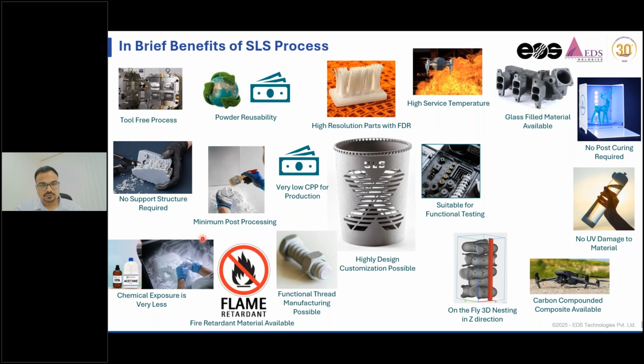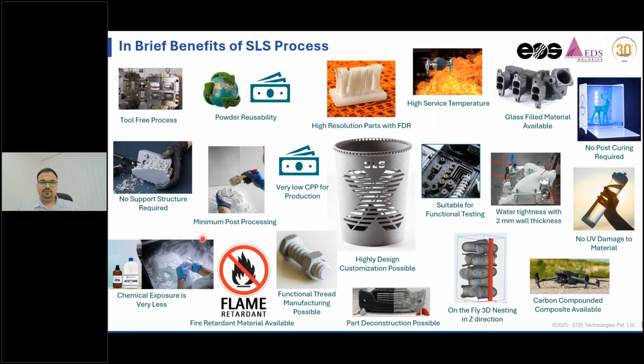fine detail resolution with us, FDR, which is able to address as low as 0.2 mm of the feature, which is used for very miniaturistic designs to be addressed and printed. And we have watertight material. Immediately after 2 mm, you can claim the water tightness on our component. So these are all benefits of SLS process.